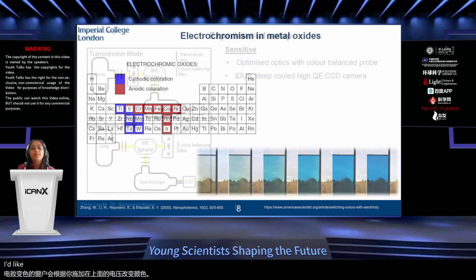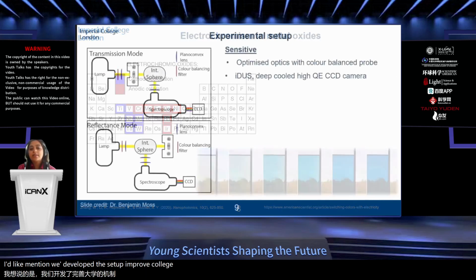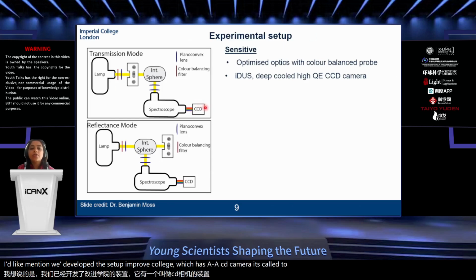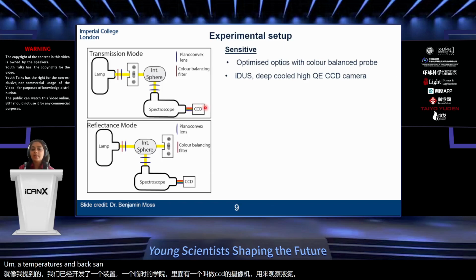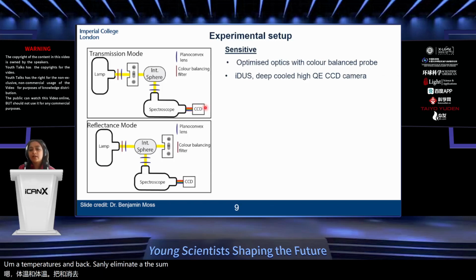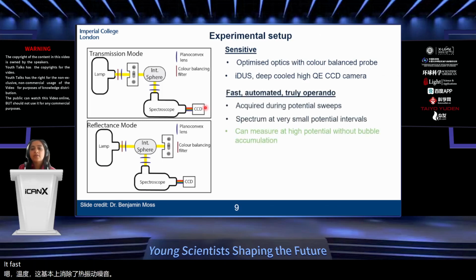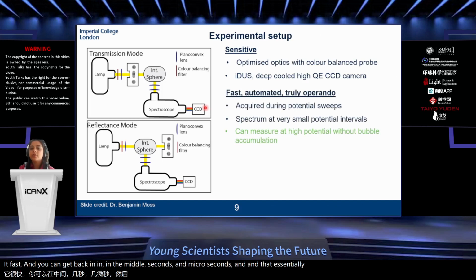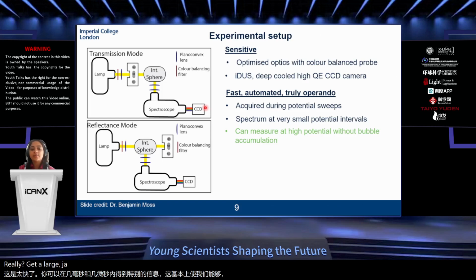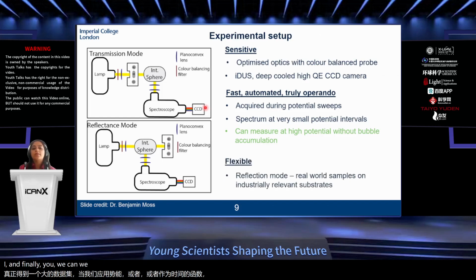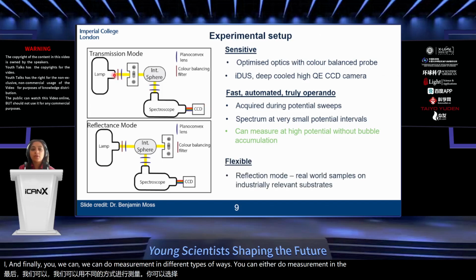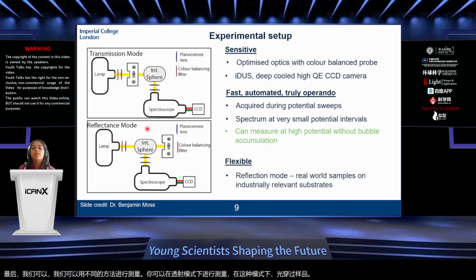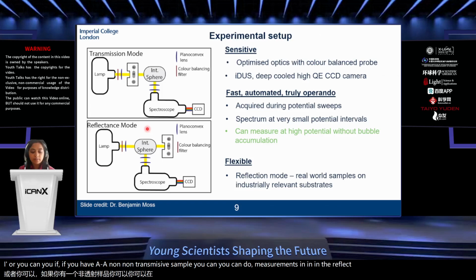So like I mentioned, we've developed this setup at Imperial College, which has a CCD camera. It's cooled to liquid nitrogen temperatures, and that essentially eliminates thermal vibration noises. It's fast. You can get spectra in milliseconds and microseconds, and that essentially enables us to really get a large data set as we either apply potential or as a function of time. And finally, we can do measurements in different types of ways. You can either do measurement in the transmission mode where the light goes through the sample, or if you have a non-transmissive sample, you can do measurements in the reflective mode, for example.